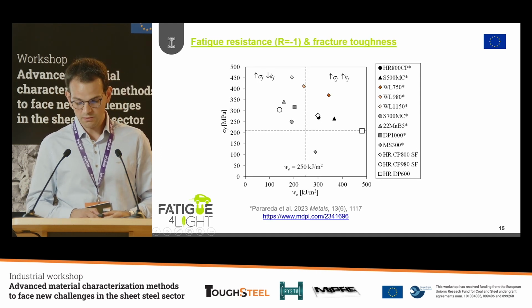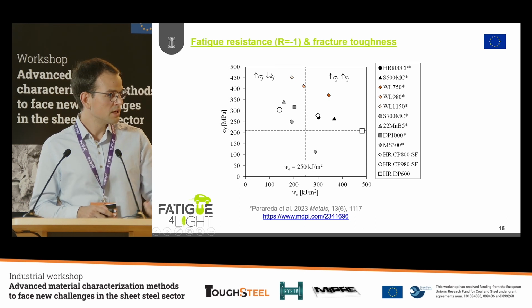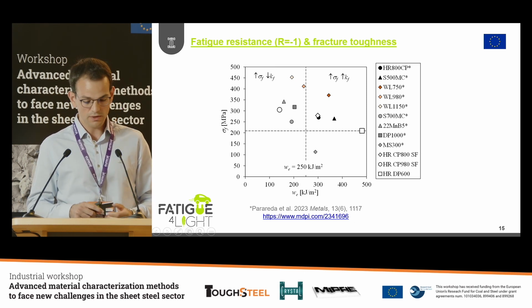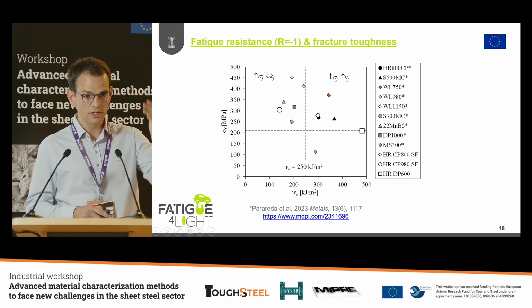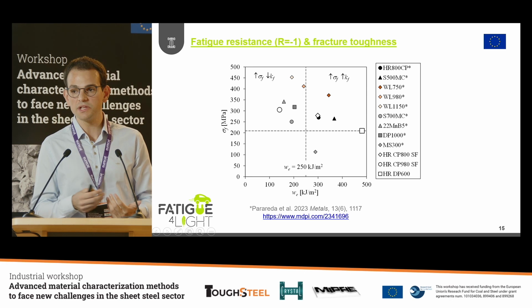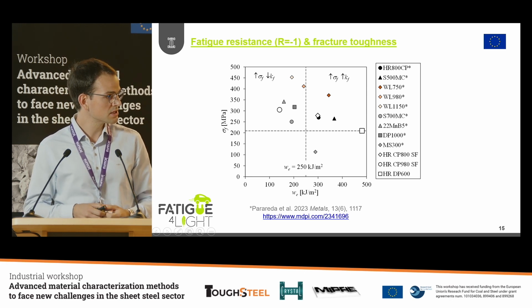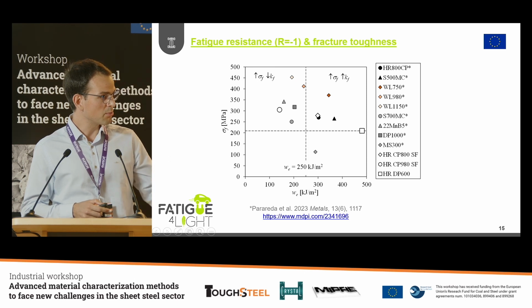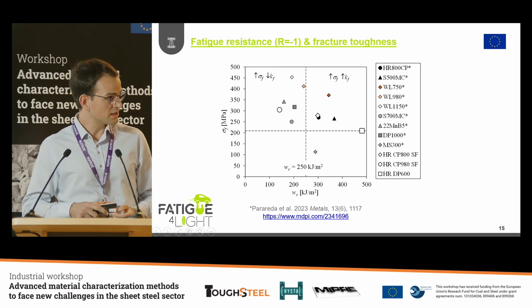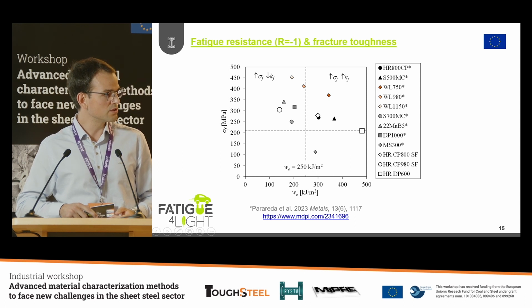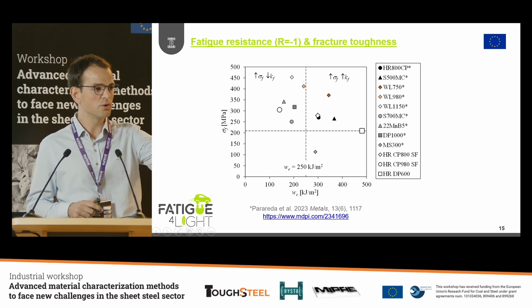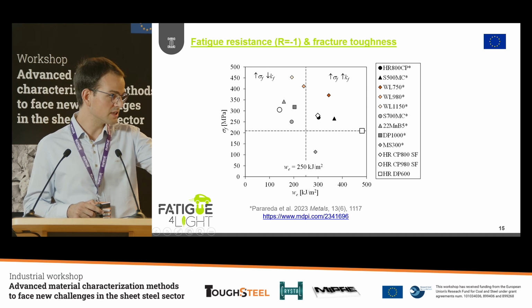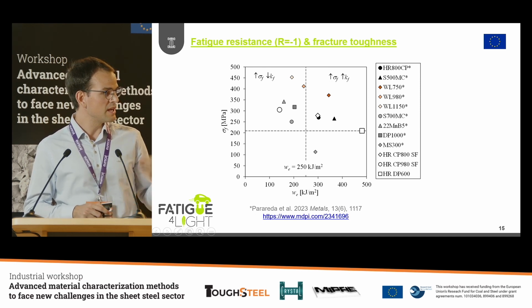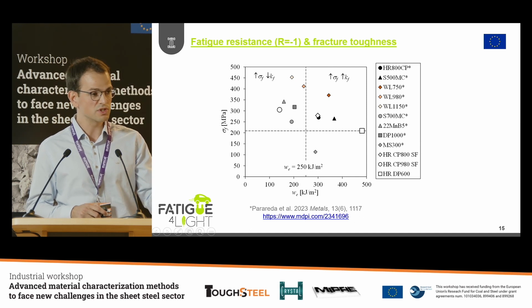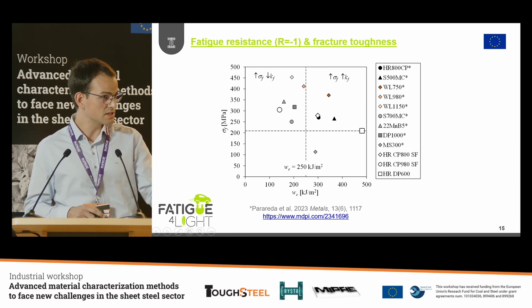But at the end of the day, what we want to propose and what we developed as a tool is this plot, where here you can see the fatigue data for the polished state. So this is, let's say, a conventional result that you can obtain from the steel makers, against the fracture toughness values. By plotting all of this data here, you can clearly see that some materials present a really good fatigue resistance, but the fracture toughness is really low. So this means that we will have a material with a good fatigue resistance, but when we have a defect there, the fatigue resistance will be completely reduced. So the main aim is to use this graph to select new materials to address this lightweight design.